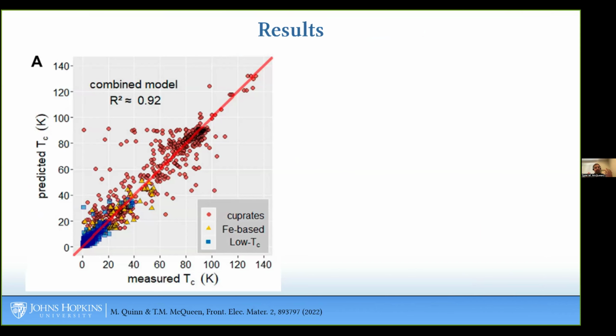And then we do all the same games that you saw in the previous work that I went through by my friends. And so now here's a plot of measured TC versus predicted TC, now on a linear scale. And it's not bad, okay? Just like, again, this is okay. It's not bad. It's certainly better than in many areas of science, the level of agreement here. But then you'll notice there's a whole bunch of real outliers here, right? Like, look at all these, right? Those all have a predicted TC that's basically the same, but the measured TC is markedly different.